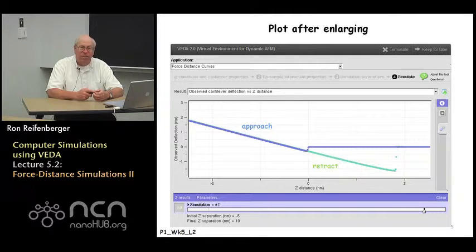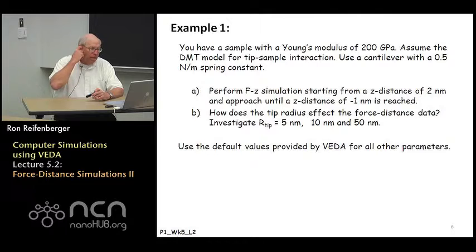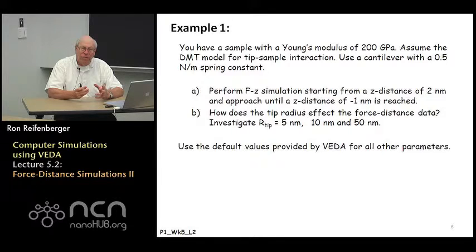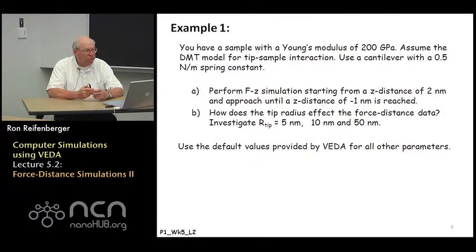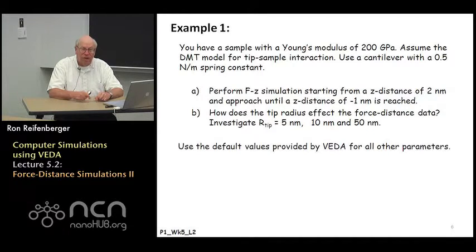These simulations allow you to understand your experimental data in much more depth than is possible just by looking at it. Now let's run through an example where we simulate different tip radii. We'll simulate a substrate with a Young's modulus of 200 gigapascals using the DMT model for tip-sample interaction. The tip radius directly influences the tip-sample interaction force, and from the second week of lectures you'll find formulas showing that the interaction potential is directly proportional to tip radius.